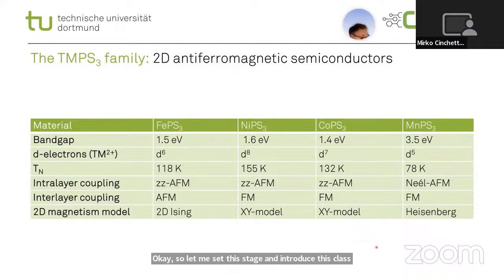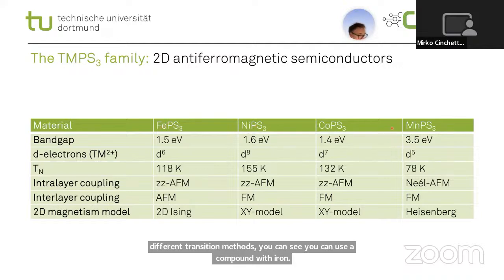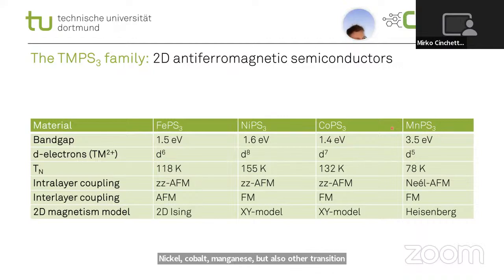Okay, so let me set the stage and introduce this class of materials. These are actually transition metal phosphorus trisulfides. And this is a very nice class of materials, which can be used also as a model system, because if you use different transition metals, you can use a compound with iron, nickel, cobalt, manganese, but also other transition metals. You can generate a family of compounds that are all semiconductors and all antiferromagnets. And this table shows that depending on which transition metal atom you choose, you can tune the band gap from 1.5 to 3.5 electron volts. But also you can change the Néel temperature from 80 to 160 Kelvin. And also, very interestingly, you can change the intra- and interlayer coupling. So as a result, these systems offer the possibility to study different models that describe magnetic ordering in two dimensions, ranging from the Ising model to XY and to the Heisenberg model.